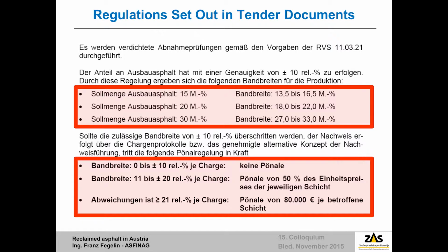One important point to be determined in the tender document was the amount of recycling asphalt to be added, the related deviation allowed, and how we regulate the penalty payments. The deviation was determined by the conditions of processing technology. The check of the amount was done by batch scales, which were included in the conveyor belts. As we had higher costs for this pilot project, we couldn't risk ending up without findings for future projects. So that's why, in this case, our penalty payments were very high.